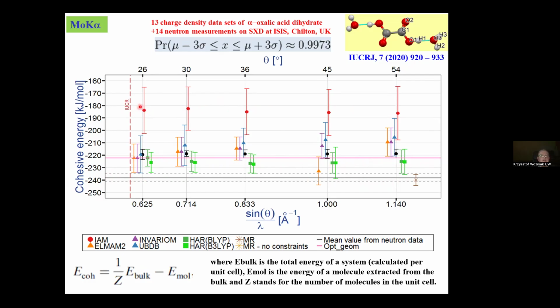So this means that when we are using the independent atom model, we can forget about weak interactions, hydrogen bonding, say pi-pi interaction, etc. However, when we standardize the data, we are getting these black points, which are in error slightly more, around 20 kilojoules per mole. And data banks are giving intermediary results between the independent atom model and HAR.